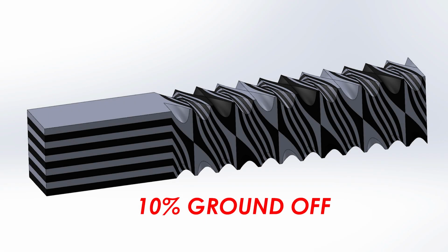Here, I have removed 10% off the face of the billet. The slanted lines resemble what we saw in the original blade, and so that's the appearance of the straight section of the billet. Not so much this hourglass pattern that forms in between. This is the result of having a black layer at the bottom of the billet. We will need to modify our laminated billet to solve this problem.